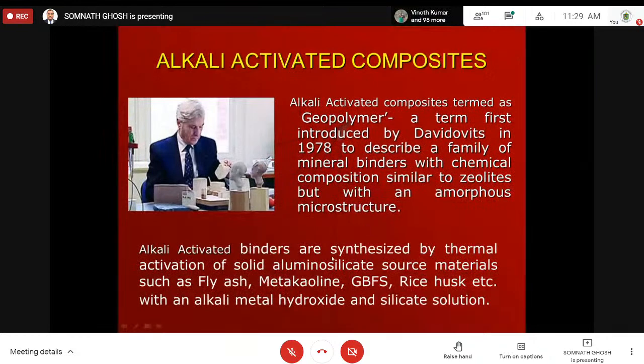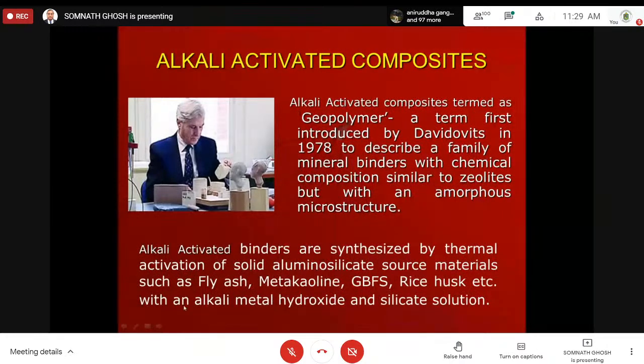Now you see, the alkali activated binders are synthesized by thermal activation of solid aluminum silicate source material. That means the source material which contains aluminum silicate, such as fly ash, metakaolin, ground granulated blast furnace slag, rice husk, etc. It contains aluminum silicate, with alkali metal hydroxide, sodium hydroxide, potassium hydroxide, or sodium silicate, potassium silicate, some silicate solution. So there is no conventional cement. Just fly ash and all these things, hydroxide, some silicate, mixed together, you will be able to produce the gel. And that gel will be able to bind the aggregates, and you will get a concrete.